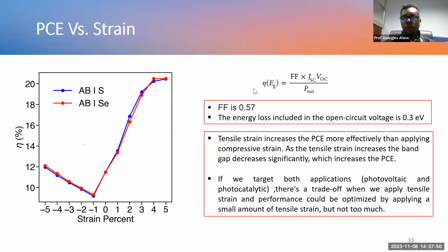And we use this formula to calculate the power conversion efficiency. For the fill factor, we have taken it from a literature. We have found that for one transition metal dichalcogenide 2D material, the fill factor is 0.57. And that is the only experimental study which is reported in literature according to our investigation. So we use that because our material is like transition metal dichalcogenide, so it has similarity. So based on that empirical value and then the formula, we have calculated these PCE values.